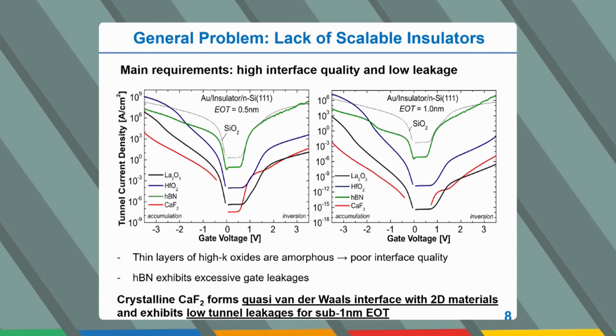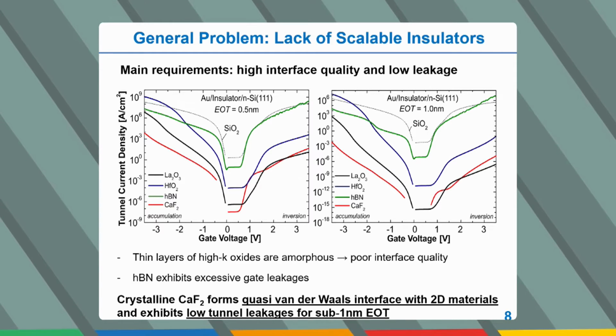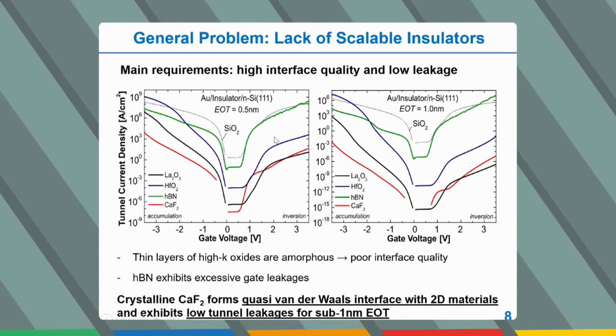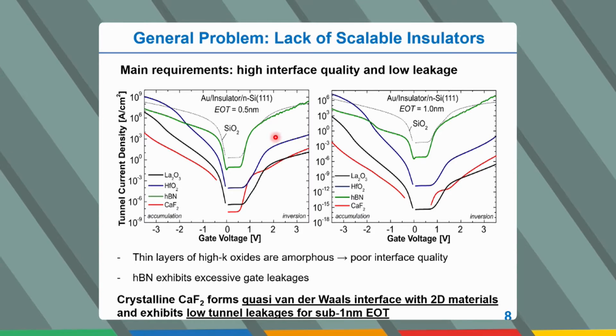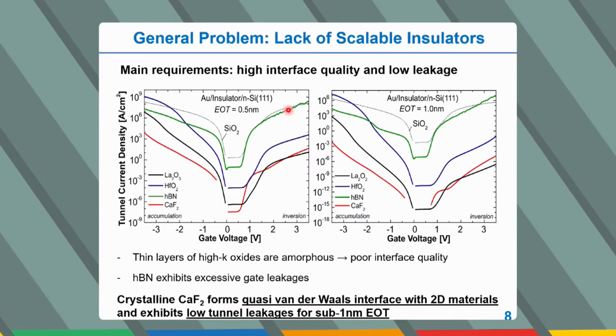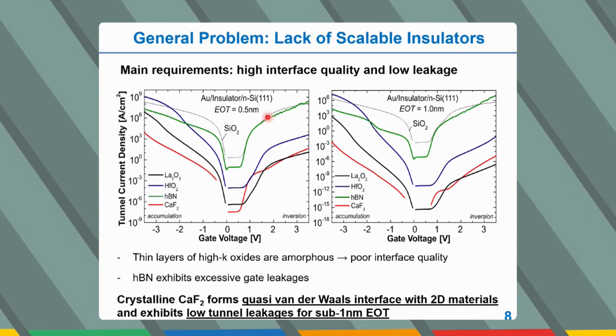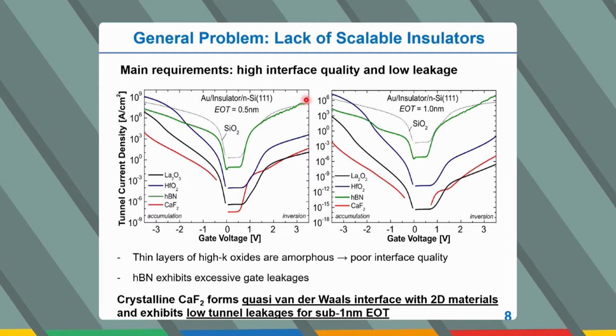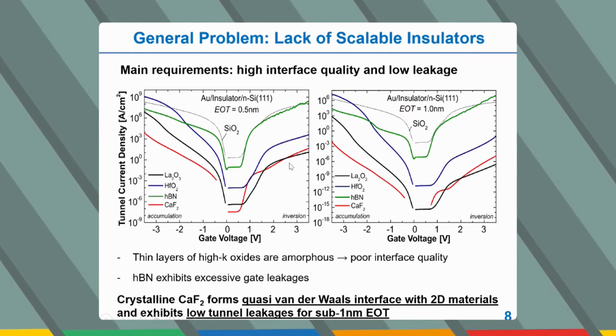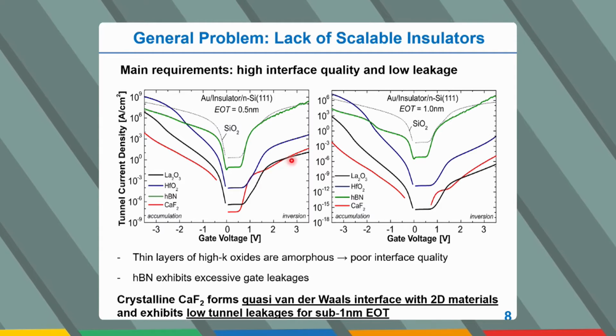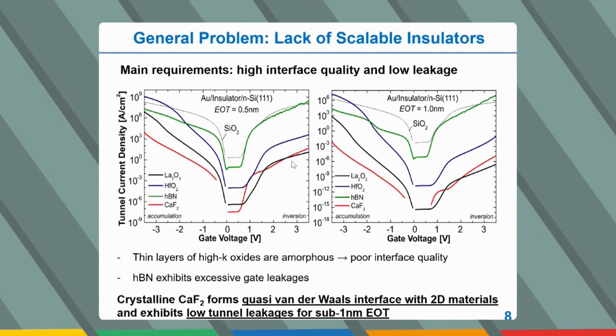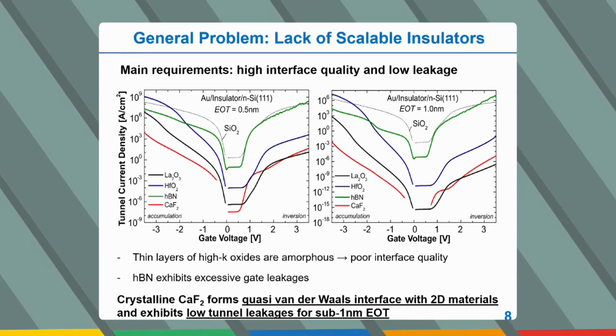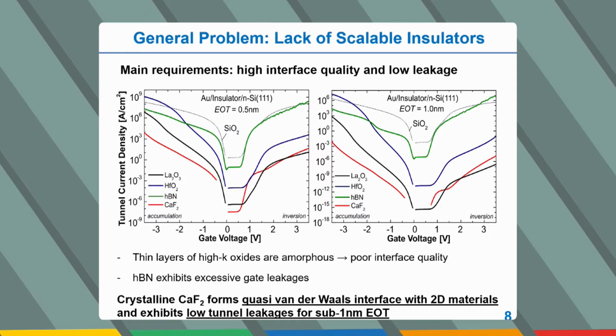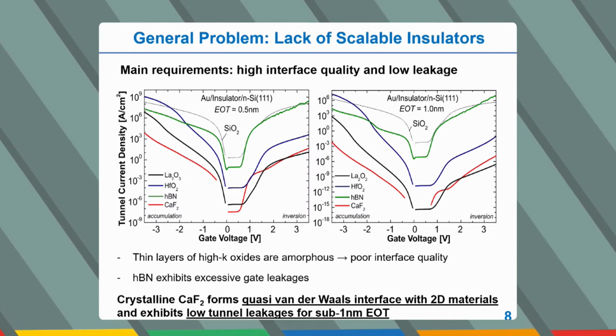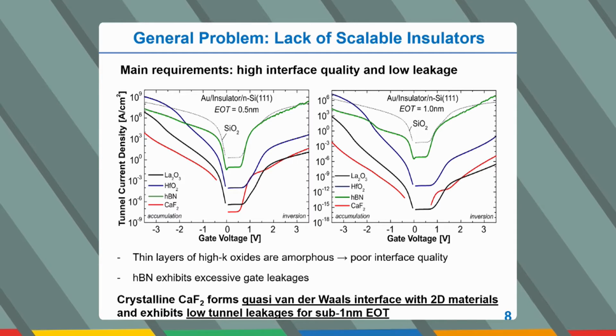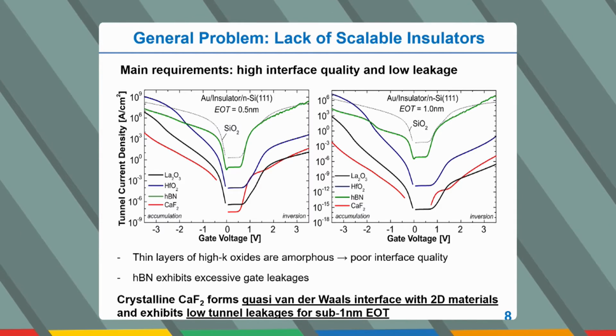But another criterion is that you need to scale down the insulator thickness, and when you scale down some insulators like hBN, which have a small dielectric constant and narrow band gap, you see that the tunnel leakage currents are very huge through such a material like hBN. So here we show modeling results for equivalent oxide thickness of 0.5 nanometer and 1 nanometer. But for a material like calcium fluoride, the tunnel leakage is relatively small, which is quite satisfying for us. So this material basically satisfies two main criteria for an insulator for 2D electronics: high interface quality and low leakage, and that's why it is so attractive, as we think, for next generation 2D electronics.